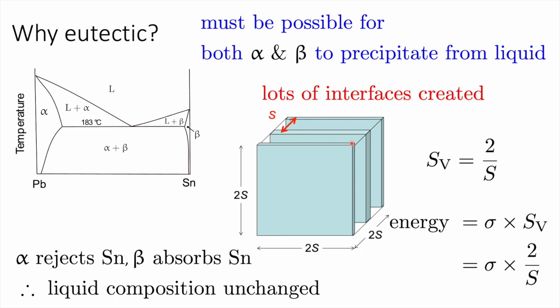So the amount of surface that I have per unit volume is 4 times 2s squared divided by 2s cubed. And if you work that out, the amount of surface per unit volume is simply 2 over the spacing of the lamella. And the energy that is locked in this surface per unit volume is simply the interfacial energy per unit area multiplied by S sub V, which is sigma into 2 over the interlamellar spacing. What this means is that the cost of creating these interfaces